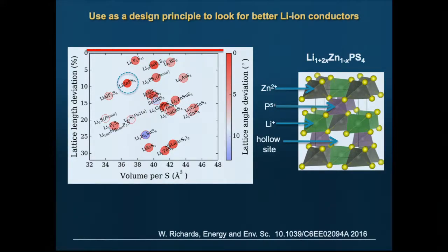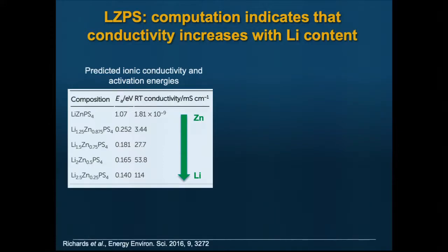It has a BCC backbone. By itself, it's not a good conductor. You have to put in carriers, so you have to lithium dope it. And we predicted that depending on the amount of lithium doping, we could get as high as 100 millisiemens.